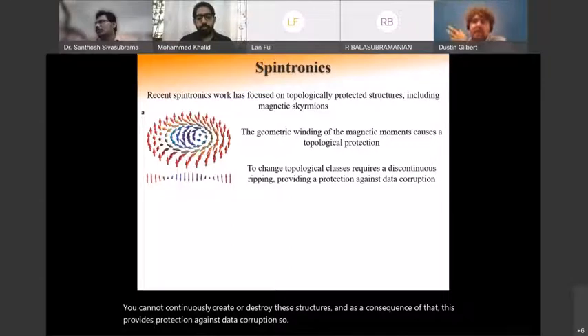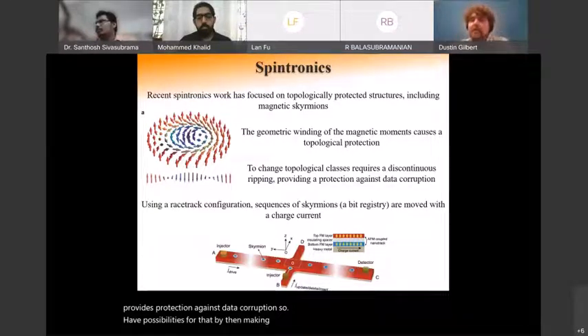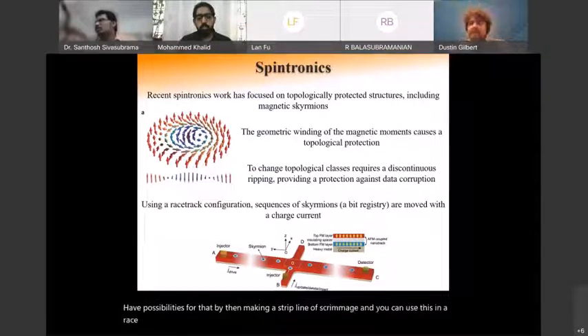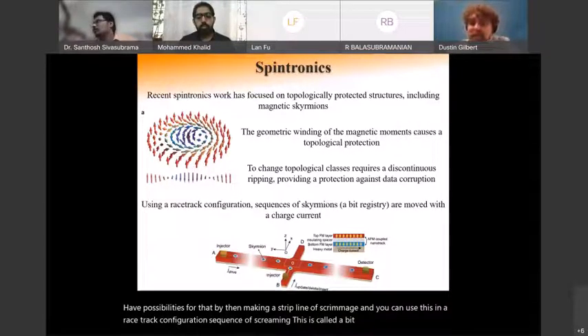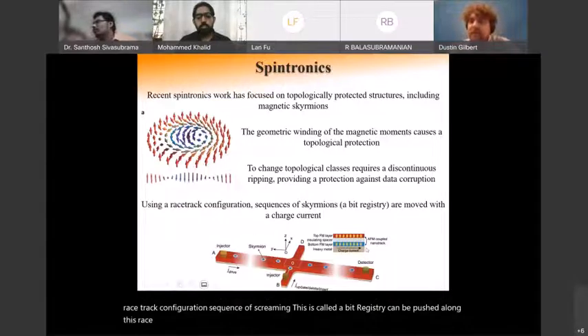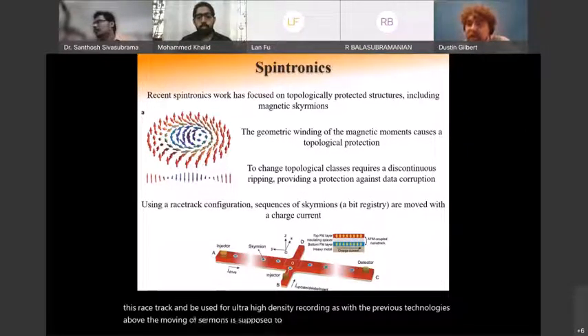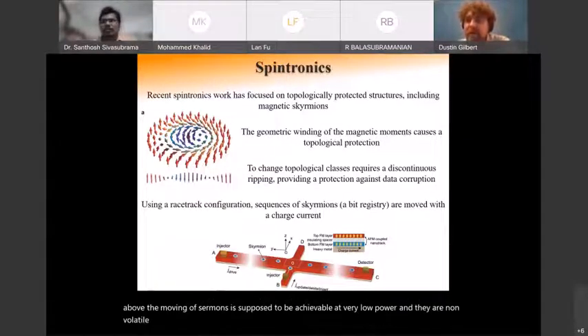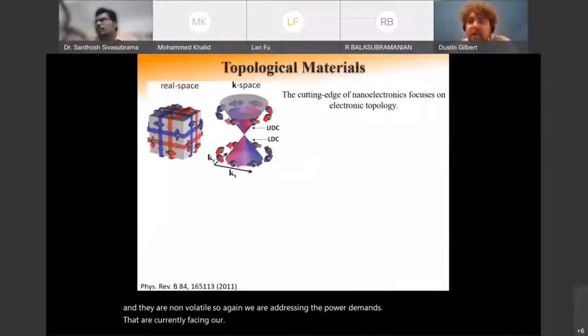By then making a strip line of skyrmions, you can use this in a racetrack configuration. A sequence of skyrmions called a bit registry can be pushed along this racetrack and be used for ultra high density recording. As with the previous technologies above, the moving of skyrmions is supposed to be achievable at very low power, and they are non-volatile. So again, we are addressing the power demands that are currently facing our electronic technologies.